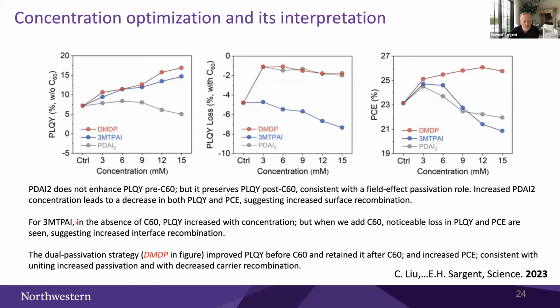And then in the case of the 3M TPAI, before the addition of the C60, we do get the increase in PL with concentration, but then if all we have is the 3M TPAI, we do lose the PL when we add the C60. And then the most interesting result is that when we use the dual passivation strategy, which is labeled DMDP in all of these figures, we do improve the photoluminescence quantum yield before we add C60, and we retain it after we add C60. And correspondingly, we get an interesting improvement in the power conversion efficiency, suggesting that we really have combined passivation with